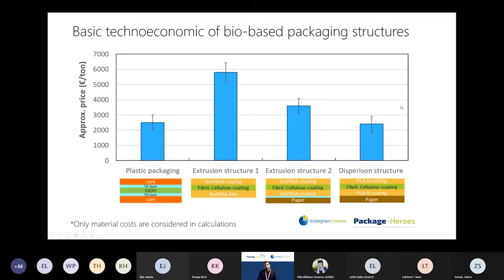But what's interesting here is that flux structure, for instance, which is dispersion-based structure, it is actually able to compete in price with the plastic-based packaging structure that we have here. The extrusion structure 1 and 2, they are slightly higher in price, but I have a feeling that if we are able to optimize these material amounts for different layers, we could also get these potentially to be able to compete with the plastic structure. Also, we need to keep in mind that these are not the industrial quantities prices. Basically, when you get these materials for piloting, you are getting them at much higher prices compared to let's say industrial scale production. So that is another reason for these slightly higher values.